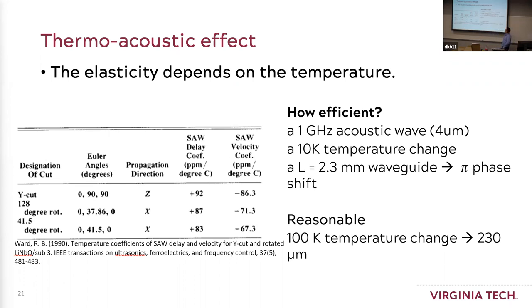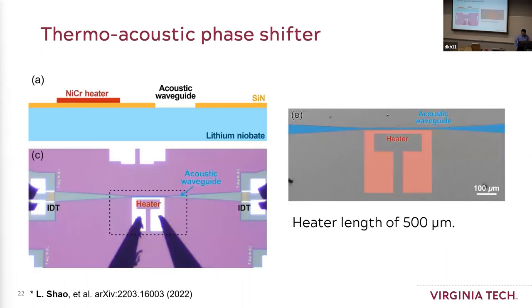What does it mean? If I have an acoustic wave at 1 gigahertz, and I change the temperature locally by a heater by 10 degrees, I only need a 2.3 millimeter waveguide to achieve a π phase shift. That's for the 10 degrees, but realistically we can heat it up locally to over 100 degrees. In that case, we can achieve a 4 pi phase shift by using only 230 microns of the device.